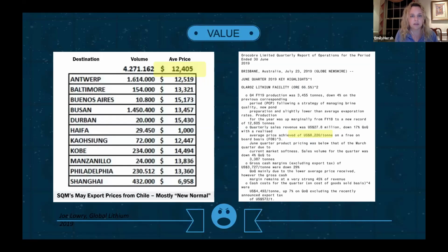This is an example of lithium carbonate, same month, same physical destinations, sold by two companies across the Andes from each other. One is Oro Cobre, which is an Australian company in Argentina, and the other is SQM, which is a lithium company in Chile. You can see that for the same product, same percent lithium, one was selling for $8,000 a ton, and the other was selling for 12.5. We are now in a pricing situation where this $12,500 per ton product is selling around 10 to 11, and this off-spec product is selling around 4,000 or 5,000.